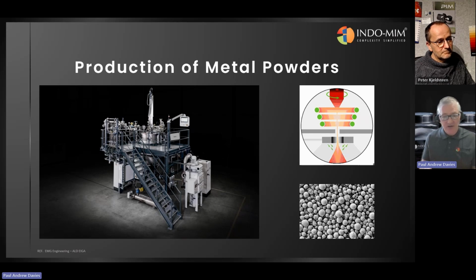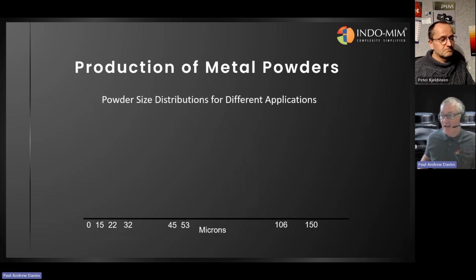And actually, the configuration of the nozzle itself is complicated, and the pressures and temperatures of the gas have an influence on the pressure just below the nozzle, and that can be negative. So it's actually blowing the molten material back up into the molten chamber if you're not careful. And especially for finer powder, you want to have higher pressures and higher temperatures, as highlighted here.